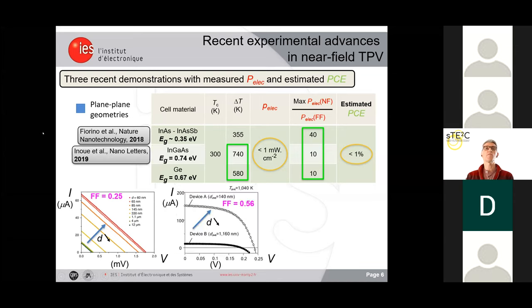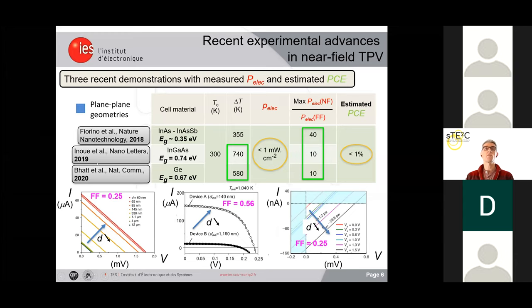In the second one, indium gallium arsenide, which has a larger band gap, was used, and a near field enhancement of 10 was obtained with a record temperature difference of 740 Kelvin. In the third one, germanium was used, and in this experiment, a near field enhancement of 10 was also obtained with a temperature difference a little bit above 500 Kelvin. But in all of these experiments, the electrical power density was smaller than 1 milliwatt per square centimeter, and the efficiency was estimated and all below 1%.